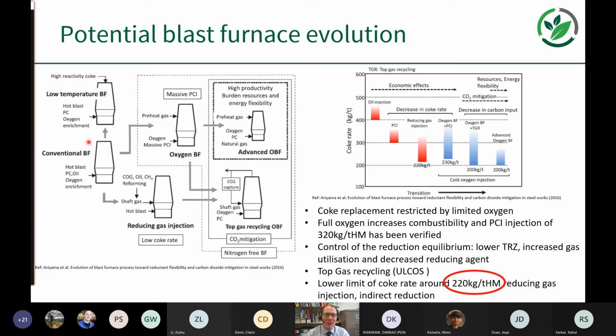So we have the conventional blast furnace represented here. A reason that the blast furnace utilizes a lot of energy is that it's a very high temperature process. So by substituting high reactivity coke, there's the potential to reduce the temperature of that process. So a low temperature blast furnace. Also then by either reducing gases such as coke oven gas or natural gas, reformed natural gas, there's more potential to reduce emissions. Oxygen blast furnace or advanced oxygen blast furnace, top gas recycling, all ways to modify the blast furnace.